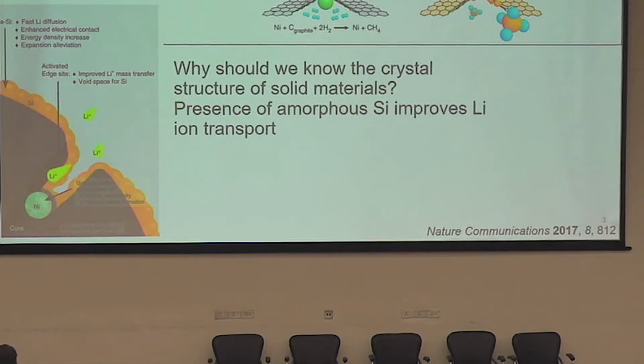So let me start off with one application, that is energy storage batteries. In this particular work, what they took was graphite and they put the element nickel on it. And they did some treatment of the nickel to get the activated graphite, which contains nickel on the surface of the graphite. And they used CVD. What is CVD? Chemical vapor deposition. And they deposited, A here stands for amorphous silicon on the surface. What they observed was, when you put the amorphous silicon, it really helps the lithium ion transfer in the lithium ion batteries. So this was a very good anode material they found out.